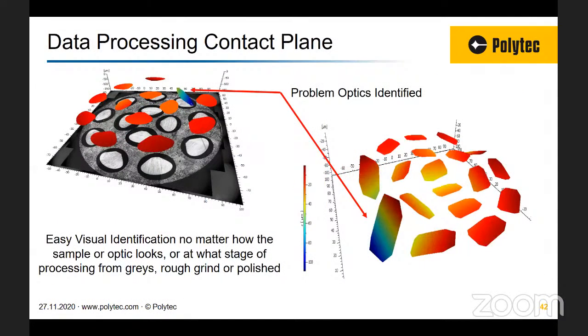And from there, we can now identify problem optics. So what we're looking to do is identify the optics which are not going to make contact to the polishing plane because they're not mounted correctly, or they're sitting too high, which could influence the behavior of how the other optics around it are equally polished. So here on the top, you can see an optic in blue. That's not in contact in relationship to the contact plane. And then on the bottom image, you can see a more rainbow colored optic. You can see this is tilted. And it's really easy to visually identify these optics once we applied the contact plane to the surfaces.